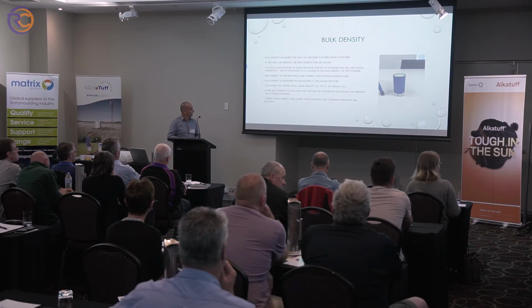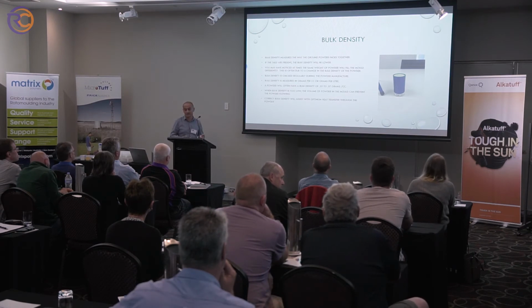When bulk density is too low, the volume of powder in the mould can prevent the powder from flowing. I'll give you an example of that in a minute. And if the bulk density is correct, it actually helps with the heat transfer into the material.